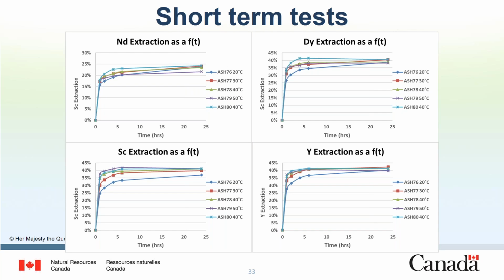Here we have the leaching of scandium and 3 REEs as a function of leaching time. The results for the other REEs are very similar. Most of the leaching in the stirred tank occurs within the first hour or two because the conditions are very aggressive and have a higher Reynolds number. Typically 25 to 50% of the individual REEs leach during the first 24 hours. The initial rate of extraction for all the elements assayed increased only slightly with an increase in temperature, suggesting a relatively low apparent activation energy.